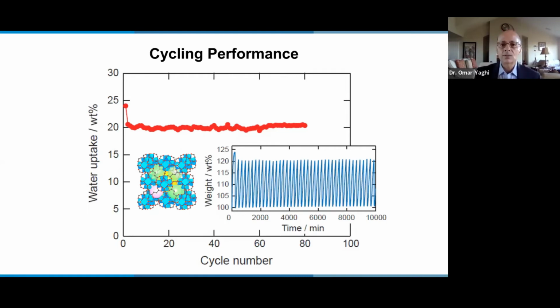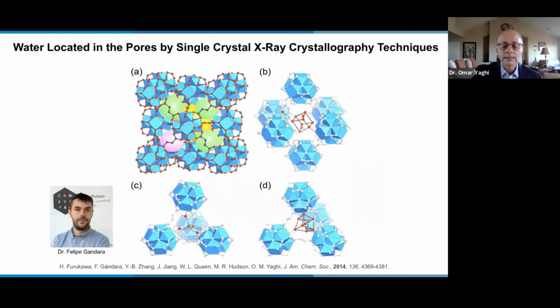So it turns out that from X-ray diffraction studies on single crystals, we find that the first water molecules to enter the pore interact with the metal oxide units, and they form a layer onto which other water molecules bind. And it was these water molecules that form in this configuration and then in these configurations that act as seeds onto which water molecules can bind and fill the pores. And these initial water molecules are not taken out during the water harvesting process. So they just sit there and they are used as seed to grow the water structure into the pores. And it is then these other water molecules that come in that in the end are taken out, and then new water comes in, and then the process is repeated.